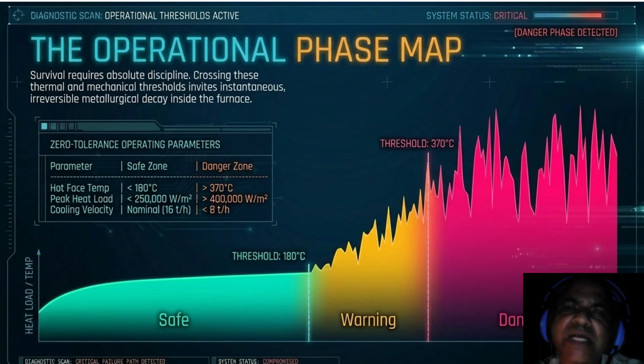The graph shows heat load over time divided into three distinct zones: safe, warning, danger. The safe zone is the green area where hot face temperature remains below 180 degrees Celsius. Once you cross that first cyan threshold, you enter the warning zone. But look at the red peaks on the right. That is your danger zone.